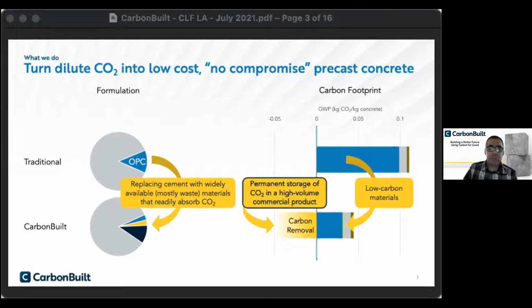So CO2 is reacting with some of these materials to form other materials that harden. And so you get a permanent storage of carbon dioxide in this product. And that, again, is a sort of a removal that acts as a negative on the overall carbon footprint. So these two things together deliver something on the order of an 80% reduction in overall emissions. About a third of that's coming from the removal or the curing with CO2, two-thirds from the change in the embodied materials.